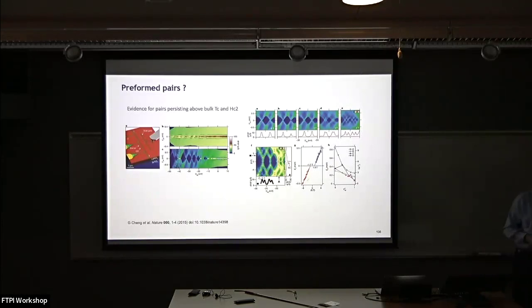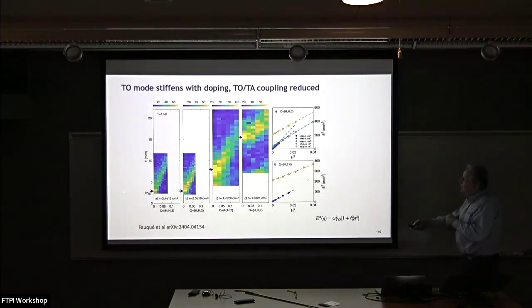The bipolaron story has one piece of data, which is data actually from Jeremy Levy's group. These are samples which are LAO-STO, so these are in an interface electron gas. And you basically made a structure with a small quantum dot in the middle, and you can tunnel on and off it. And you see these lozenges associated with this. They're associated with 2e. So two electrons come on and off, so you know that. And furthermore, they persist at temperatures well above HC2. And then lastly, what I want to show you is that as you dope, the TO mode does stiffen.